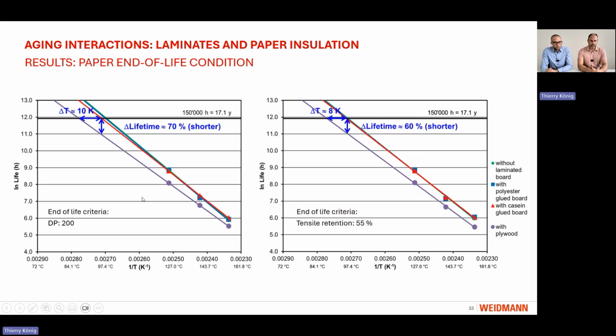values and plot them into this curve to look at the end of life condition of the paper. So we take an end of life criterion of DP200. We put in when this value was reached at 155 degrees, 140 degrees and 125 degrees. And then, as Lars mentioned, we can extrapolate this curve down to a certain temperature, to see the impact on the lifetime when the paper is aged together with this laminated material.